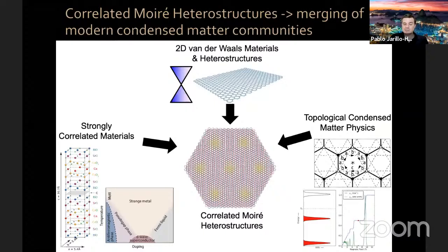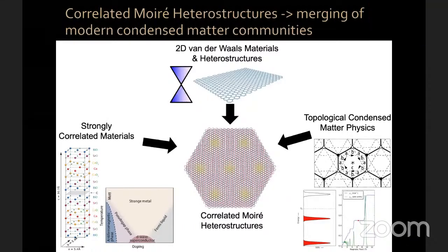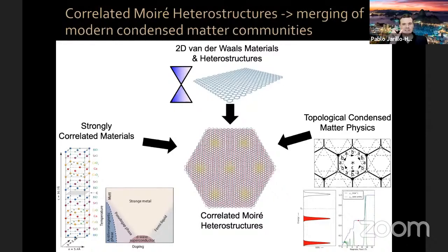So in the original prediction by Allan MacDonald, he predicted a series of magic angles. The first was 1.1, and then they go sort of as 1 over n. So the second magic angle is about 0.55 degrees, the third, etc. So far, we have not been able to find exotic physics at those higher magic angles. Now, it turns out when you go below about 1 degree, maybe 0.9 degrees, there is very substantial relaxation of the atomic lattices. And that changes the band structure such that these other higher magic angles may not be as robust as the first one. So the community is still investigating to what extent there are those higher magic angles given this relaxation.